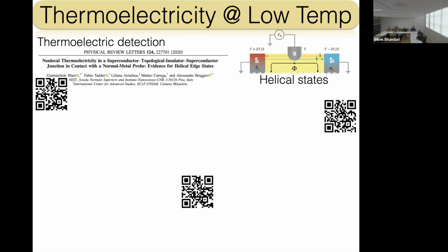And we realized that doing, for example, non-local thermoelectricity is a very clever way to get information about the helical state, because essentially here you have a situation where you see clearly that even if you have a system that is particle-hole symmetric, you can have thermoelectricity, because the real symmetry that you use in the thermoelectric effect is the symmetry between positive and negative energy states. Instead, the particle-hole symmetry is a different thing.